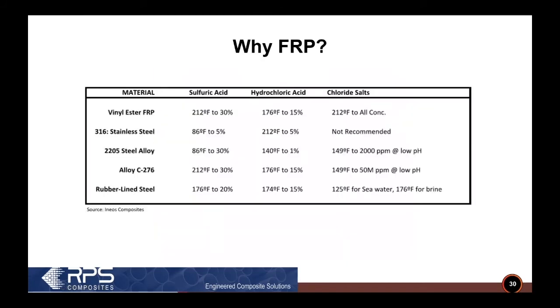So why would you use FRP piping? Well, as you guessed, you're going to use it for corrosion resistance. If you look at this table here that compares vinyl ester FRP to 316, that should say L, I think, stainless steel piping, 2205 alloy, C276, and rubber lined steel, and we're looking at sulfuric acid, hydrochloric acid, and chlorides, you can see the vinyl ester resin really outperforms them all when it comes to corrosion resistance. And actually the temperature resistance of the alloys is not much different than the vinyl esters. It's actually much lower for certain concentrations of chemistry. So basically the reason you're going to use FRP is corrosion resistance.